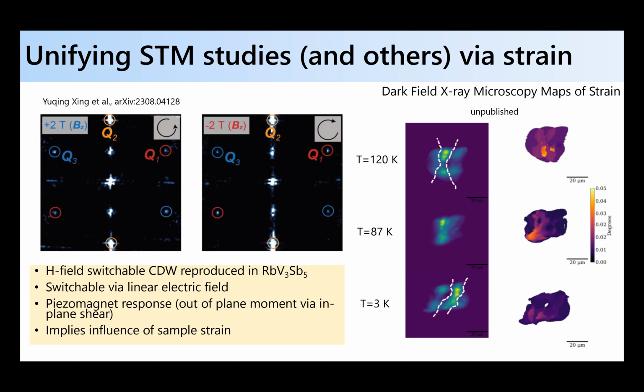Yeah, so maybe if I'm allowed to comment on this, if there's enough time. I don't know anything about the STM, but when you have 6 peaks, because of the Fourier transform nature, plus K and minus K intensity has to be identical. Plus K, this point and that point, has to be identical. When you have 6 peaks, that means you have only 3 peaks left in terms of intensity. Then the only way you can do is either 1, 2, 3, or the other way, 1, 2, 3. That's the only way you can do.